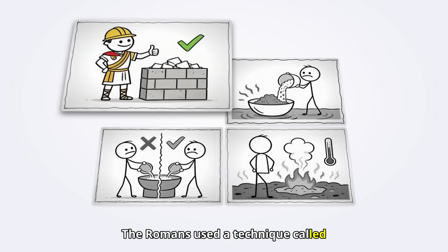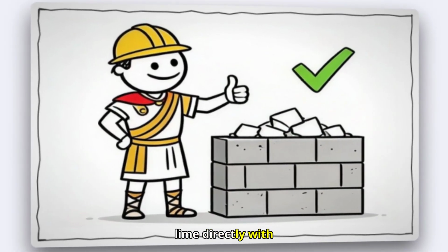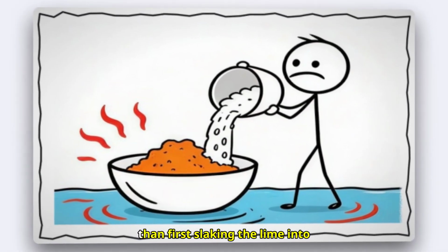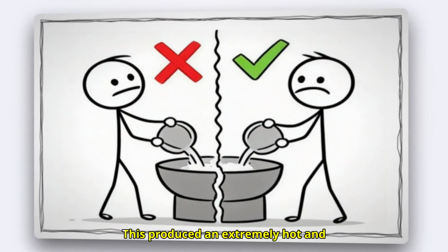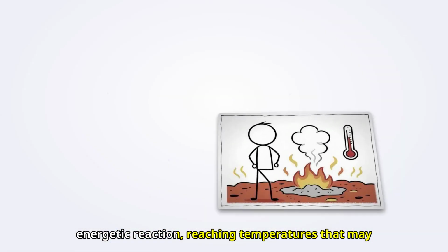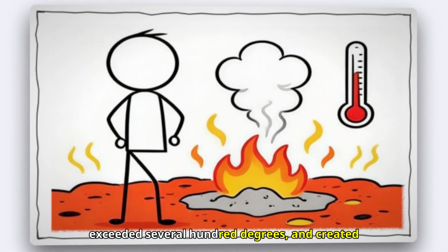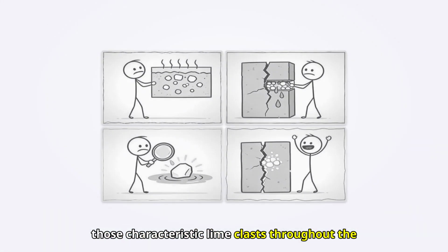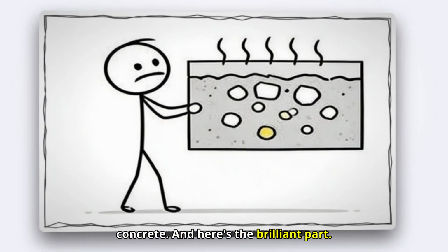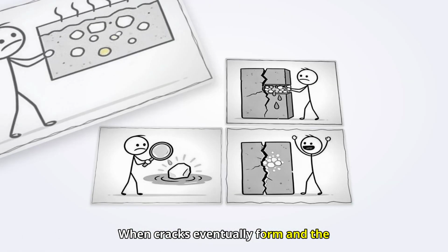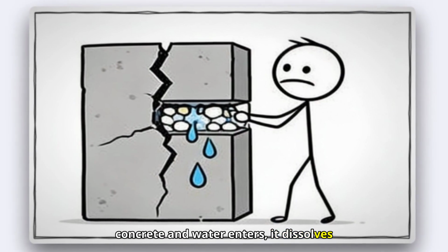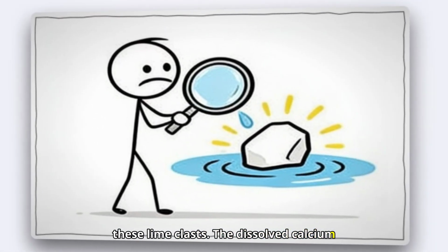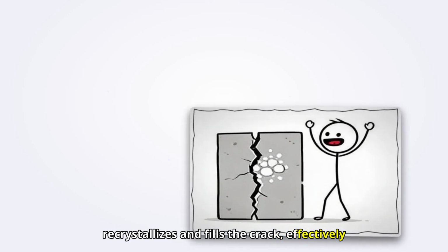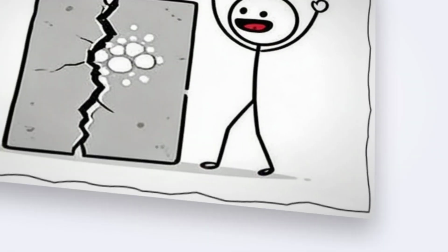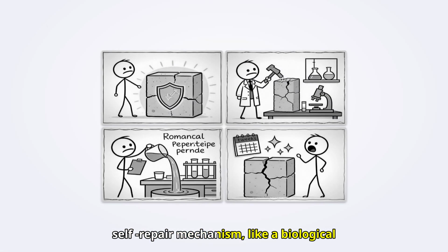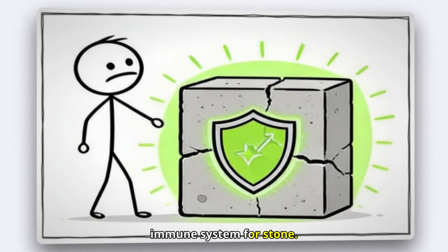The Romans used a technique called hot mixing, where they combined quicklime directly with the pozzolanic ash and water rather than first slaking the lime into a paste. This produced an extremely hot and energetic reaction, reaching temperatures that may have exceeded several hundred degrees, and created those characteristic lime clasts throughout the concrete. And here's the brilliant part. When cracks eventually form in the concrete and water enters, it dissolves these lime clasts. The dissolved calcium then recrystallizes and fills the crack, effectively gluing the concrete back together. The material has a built-in self-repair mechanism, like a biological immune system for stone.